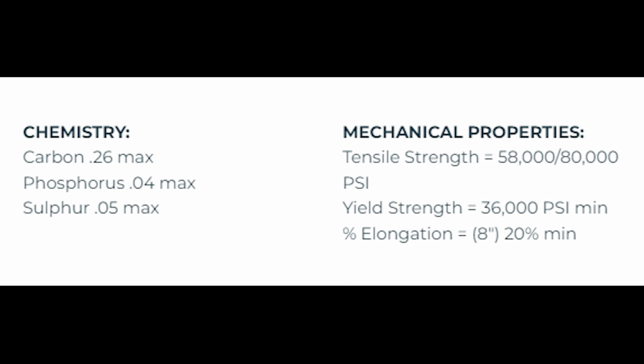This is what they claim the specs are. And you can see it's 58,000 to 80,000, so a very wide range of tensile strength. The yield strength is particularly low though at 36. What that means is, like you saw in the video where the plate starts bending, but it just doesn't give up. So that's where we're getting that yield strength from, being low, and it actually holds on for quite some time. My particular steel is probably testing closer to the 80,000 mark, because if it was at 58,000, I think that the 6010, 6011, 6013 would have held on and wouldn't have broken. So, I definitely think it's on the higher side, especially because it's 3/8 plate.